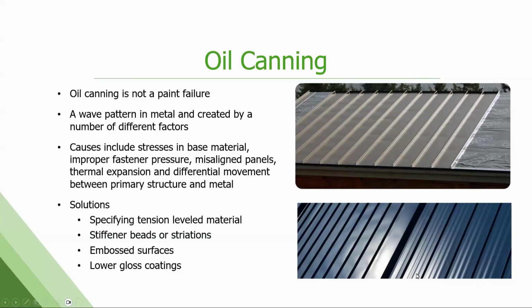We recommend striations or pencil ribs. So this is on the exact same roof, panels without the striations and panels with the striations. And you can see that you get rid of all that buckling and waviness by doing that. Low gloss coatings too, the matte finishes hide a multitude of sins. You don't get that reflection off the surface.